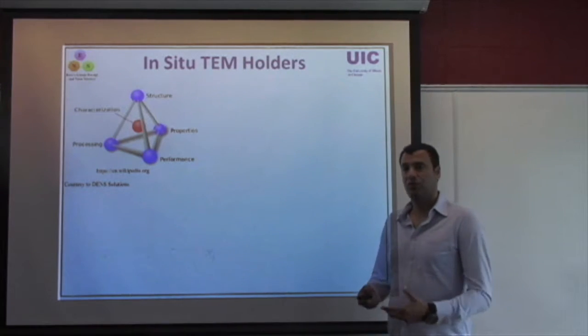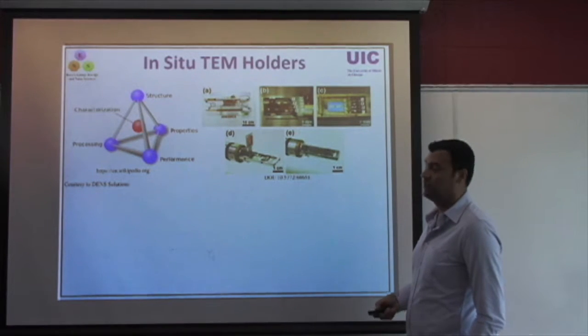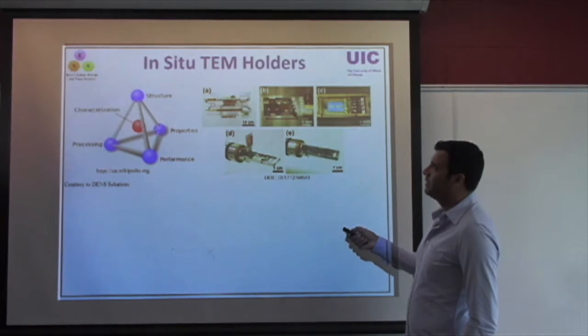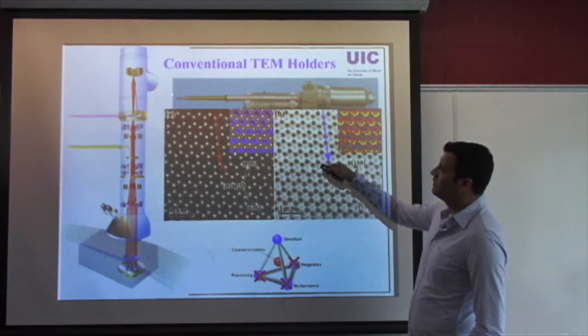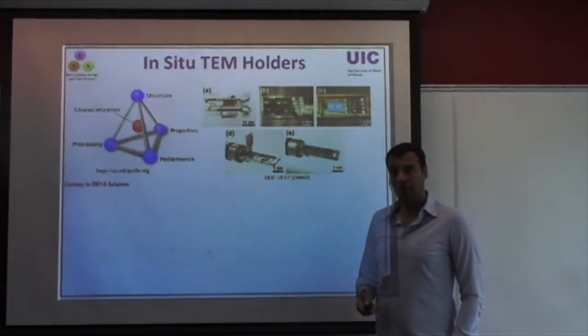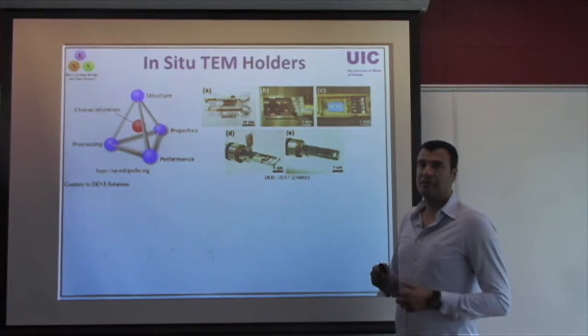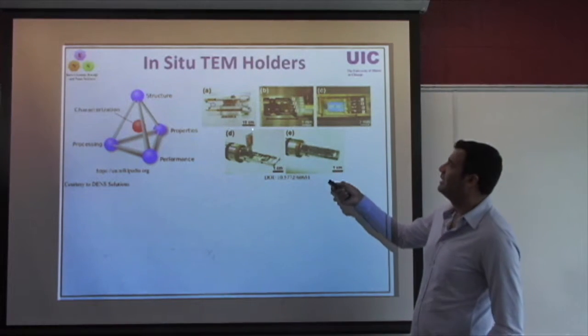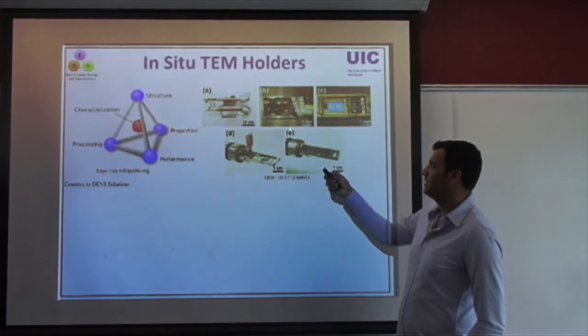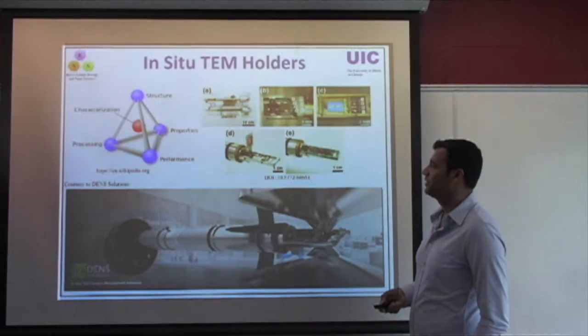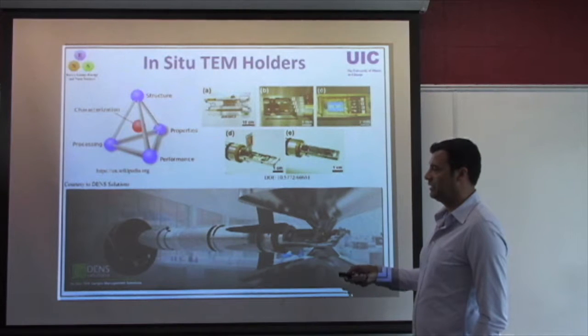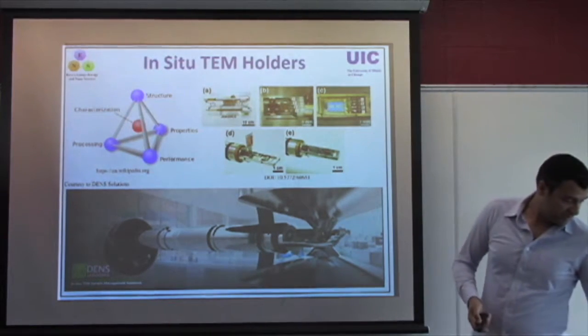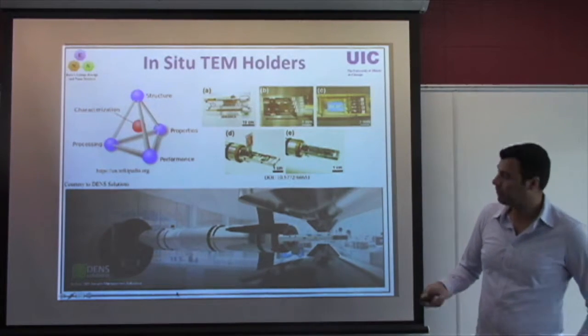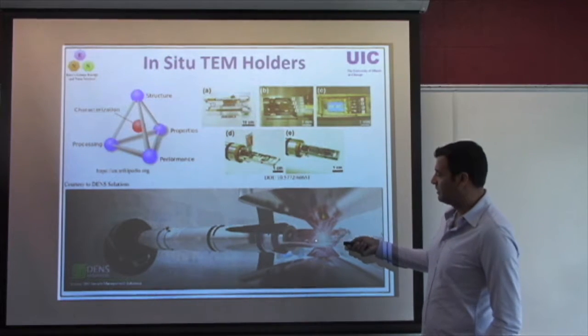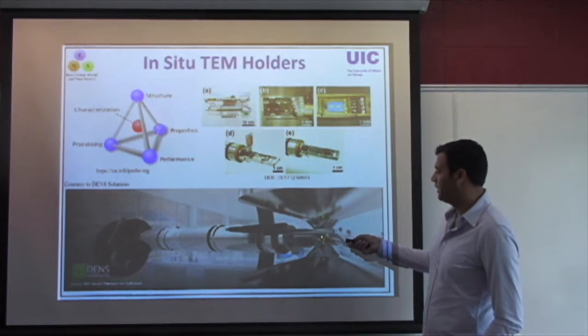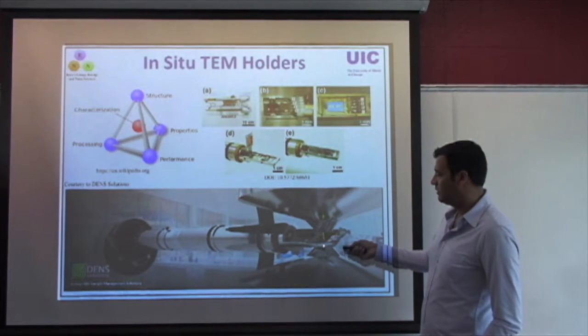And that's where in situ electron microscopy can make a great contribution. I mentioned the tip of the holder. Along the years, there has been great development to improve the holder design in order to allow you to induce some sort of stimuli or measure the properties of the materials. And there are several reviews in the field that you can take a look at in terms of the design of the stages and the holders. I'll show you one example of a holder designed by DENSsolutions. In this configuration, what you observe is that the sample is typically at the very tip of the holder, you can tilt it so you can go to different zone axes and different viewing angles, and electrons usually pass through the sample, and you can get a nice image.